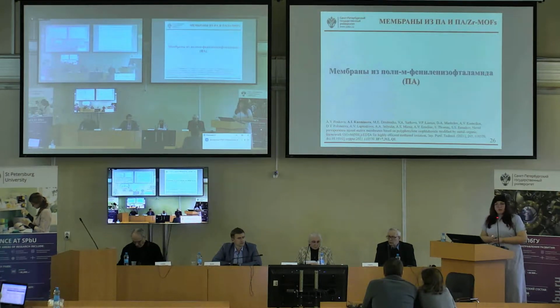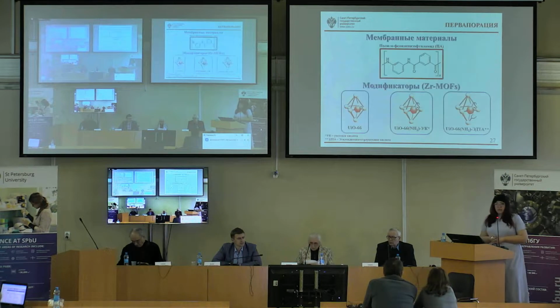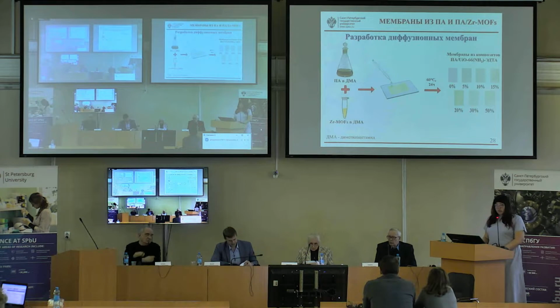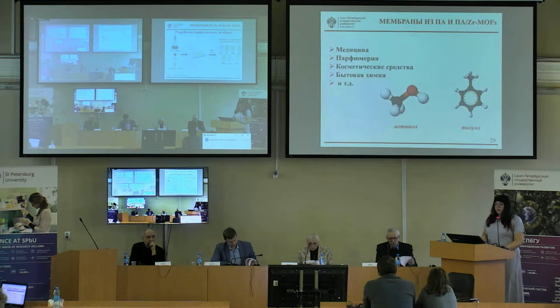The next polymer studied was poly-m-phenylene isophthalamide. To improve the properties of polyamide pervaporation membranes, 3 ZR-MOF organometallic framework structures were added to its matrix. The resulting dispersion was applied to a glass substrate, followed by evaporation of the solvent.